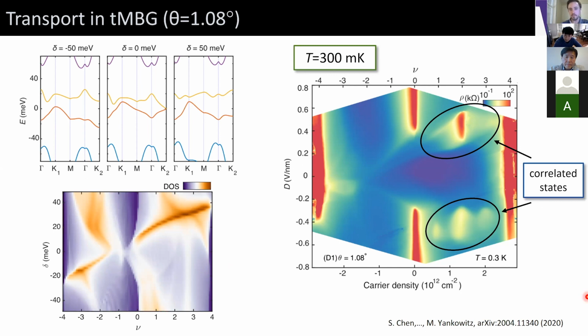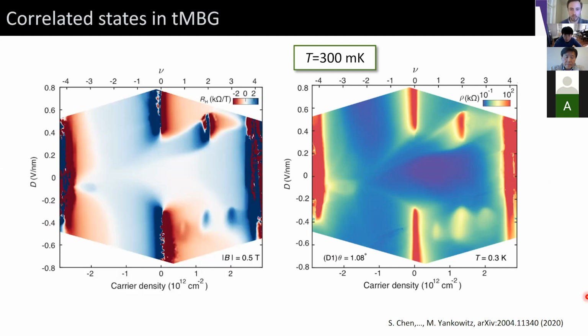All right, and again, we can play the same game where we measure the Hall resistivity. And again, we have regions around these correlated insulating states where the Hall resistivity either flips sign broadly over this extended halo region, or takes short excursions to the wrong sign around these 3 correlated states at quarter, half, and 3/4 filling on the negative displacement field side. So that's suggestive that correlations are somehow creating some sort of symmetry-broken renormalization of these bands.